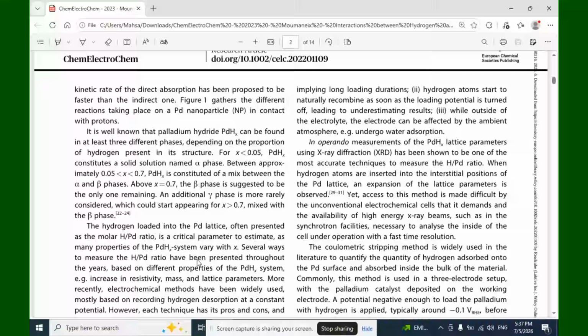Thus, implying long loading durations. Hydrogen atoms start to naturally recombine as soon as the loading potential is turned off, leading to underestimated results. While outside of the electrolyte, the electrode can be affected by the ambient atmosphere, for example, undergo water absorption.